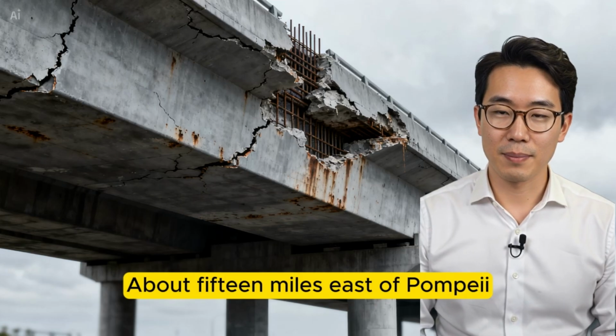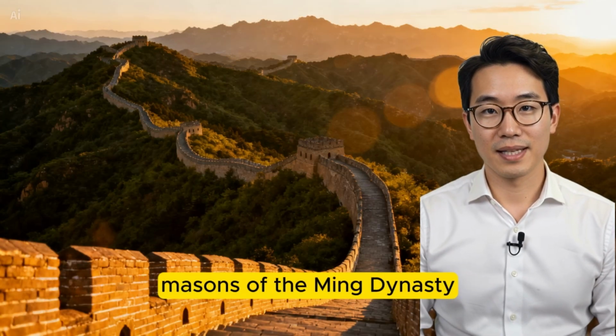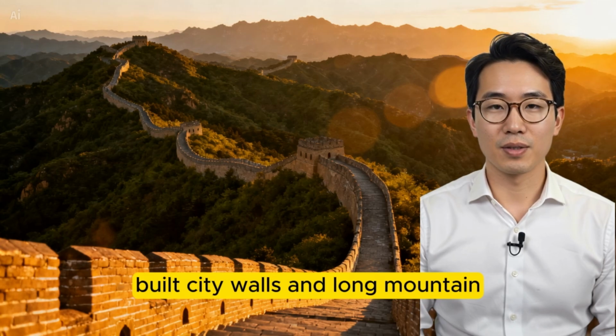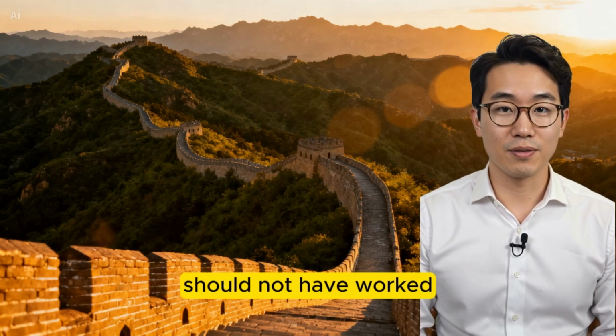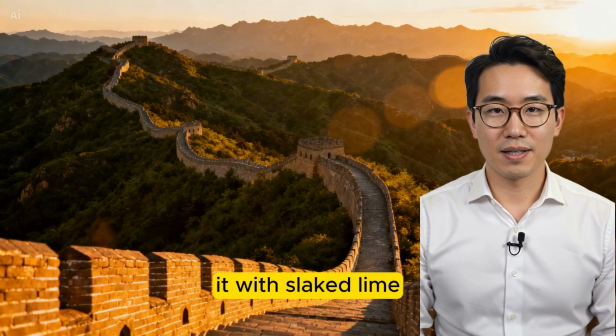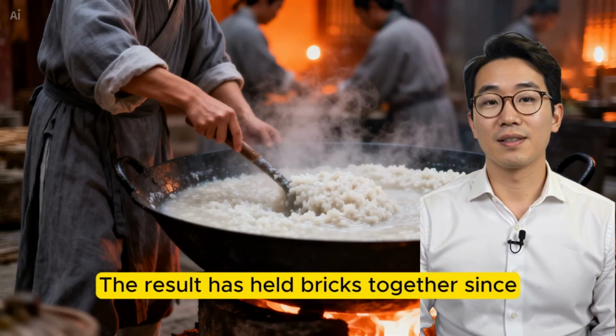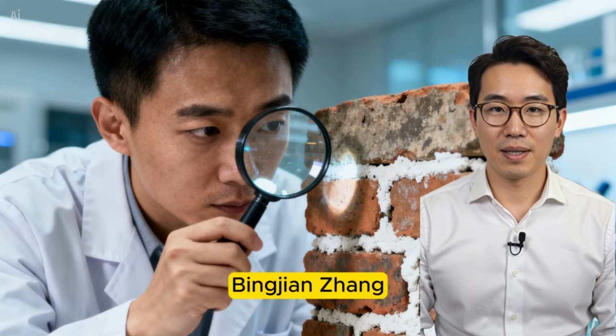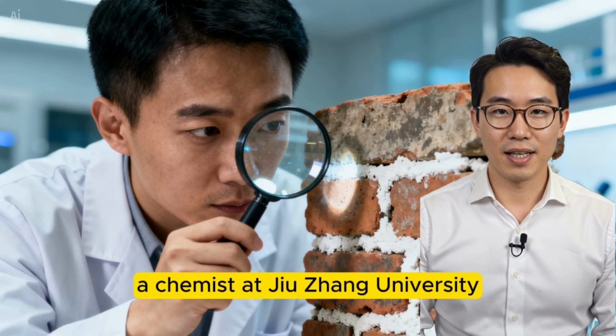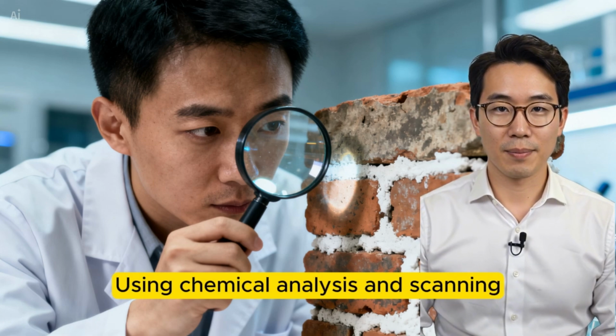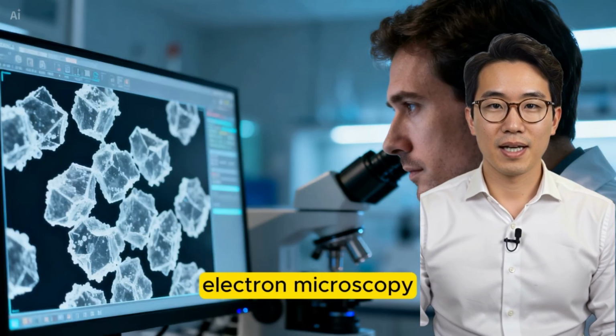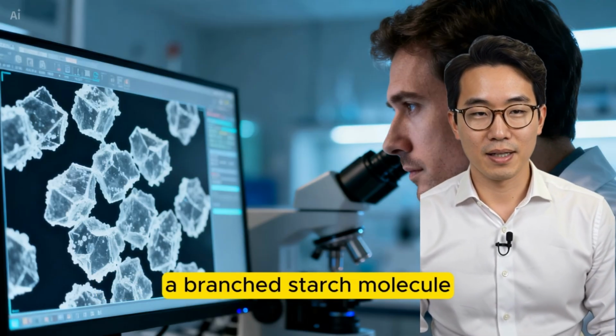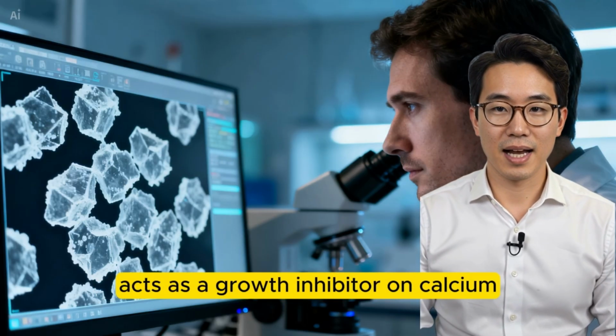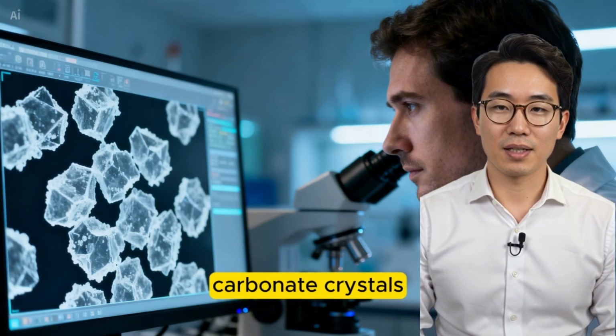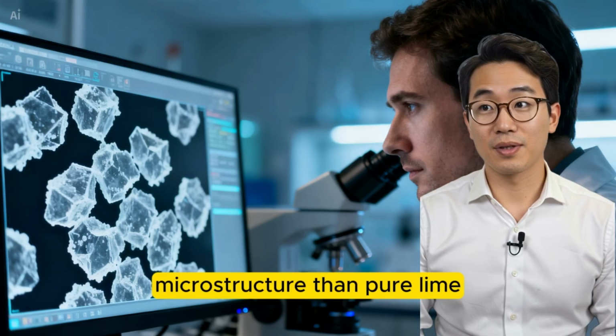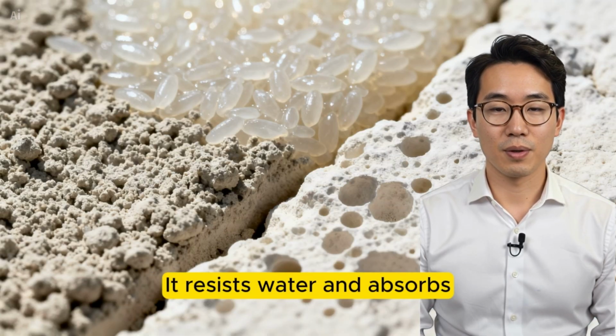Roughly 14 centuries later, masons of the Ming Dynasty built city walls and long mountain stretches of the Great Wall using a mortar that should not have worked. They cooked sticky rice into a porridge and mixed it with slaked lime. The result has held bricks together since. Bingjian Zhang, a chemist at Zhejiang University, led the team that figured out why. Using chemical analysis and scanning electron microscopy, Zhang's group showed that amylopectin, a branched starch molecule abundant in glutinous rice, acts as a growth inhibitor on calcium carbonate crystals. The mortar develops a denser, finer-grained microstructure than pure lime. It resists water and absorbs earthquake shocks.